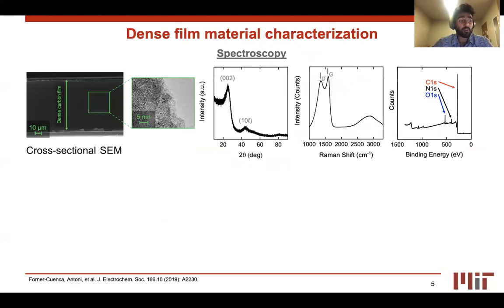First, in the dense film material characterization, a suite of spectroscopy was carried out to characterize the dense carbonaceous electrodes. The SEM cross-section on the left clearly shows that the synthesized electrodes are in fact dense. Further magnification of the SEM on a nanometer scale shows that the carbon structure is amorphous and semi-crystalline. Next, the wide-angle XRD spectra shows two peaks at the carbon crystallographic planes 002 and 10L respectively.